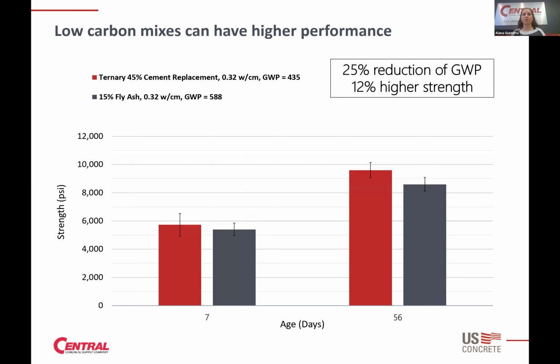And then what this is an example of is showing some field compressive strength examples where we've got in the gray bar, that's a mix with a higher GWP. It's 15% cement replacement, compared to the red bars, which is a 45% cement replacement mix and has a lower GWP. And with this, you're seeing that we don't have to sacrifice performance of the material in order to have this lower embodied carbon concrete.